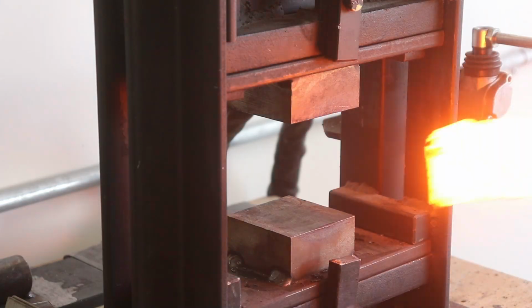So, now we are back in the forge for the third and final welding heat. On this heat, as soon as I get it into the press, I like to forge on the sides of the billet rather than on the top and the bottom, because if you are hot enough, you can make sure that any cold shuts that you have all along the edges get sealed up nice and tight, and that way you can have a billet with no delaminations in it, with the exception of the very ends. You will almost always have a little bit of sacrificial steel on either side, but that's okay because we're going to have to cut and stack this anyway, and wasting a little bit of steel just comes with the territory of making Damascus.